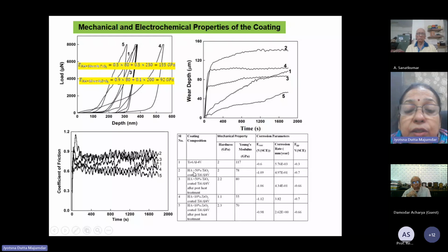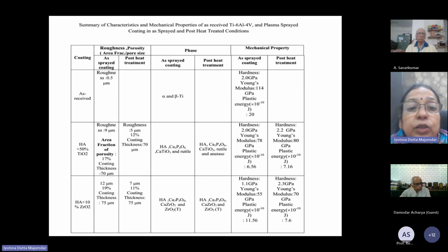So because of the hydroxyapatite coating, the corrosion or dissolution rate of the surface is higher. Hydroxyapatite offers bioactivity, but it doesn't really offer good corrosion resistance of the surface, though that is not required because hydroxyapatite is bioactive in nature. It doesn't cause any toxic effect in the human body.